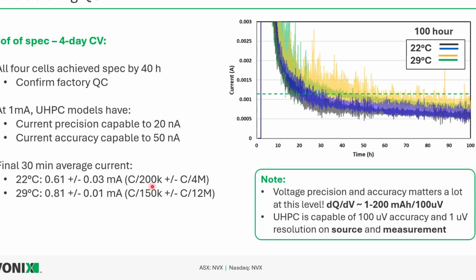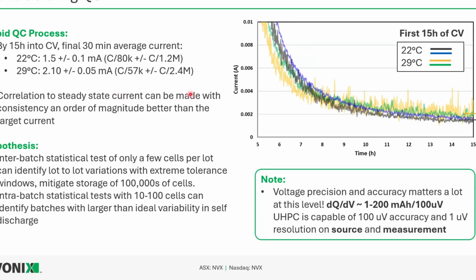So how fast can we make this happen? If we now shorten that time and look at maybe just the first 15 hours of that CV hold, we can see the 29-degree cells, maybe their kinetics were a little faster, so they dropped in current and then stabilized. And then the 22-degree cells followed suit and stabilized around the 15-hour mark. So maybe we can use that. We can see that these are also very consistent between the cells.